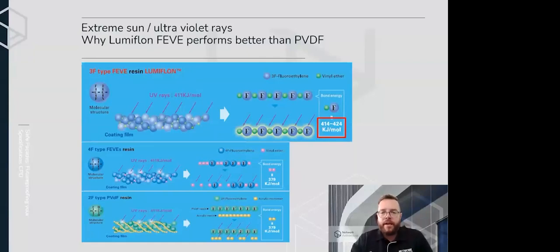So the PVDF and standard FEVE breaks down as the bond energy is less than the UV rays. So you can see that the FEVE Lumiflon has a bond energy of 414 to 424, whereas the PVDF down the bottom is 379, while the UV rays of 411 kilojoules per molecule are constant over all three. Now the UV rays at 411 kilojoules per molecule, that's as strong as it can be. So you can see the bond energy of the FEVE is 414 to 424. It's stronger than it, so it's not going to break down. With the PVDF, over time, it will begin to fade and break down that color.